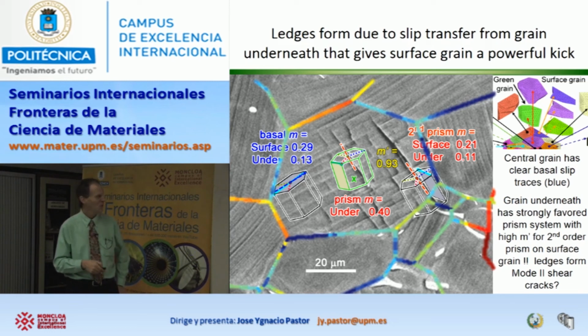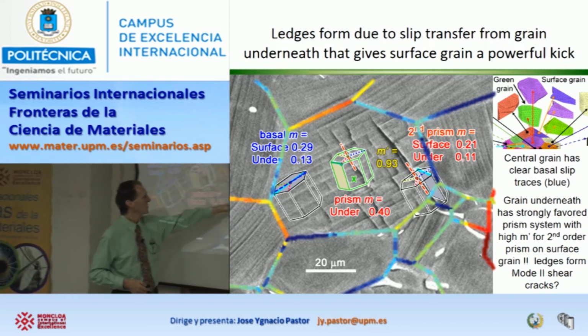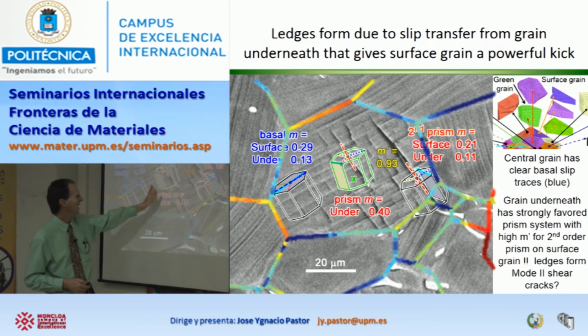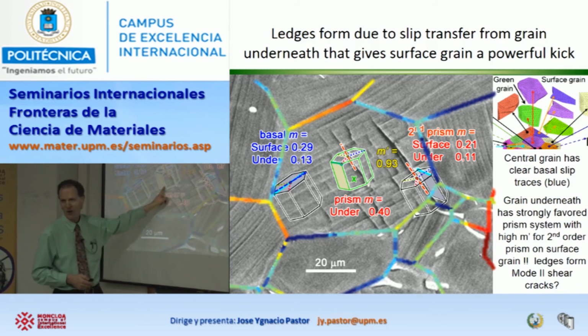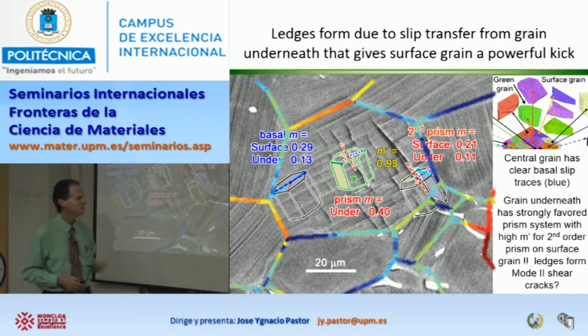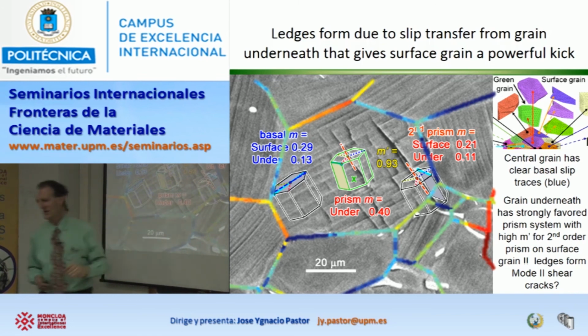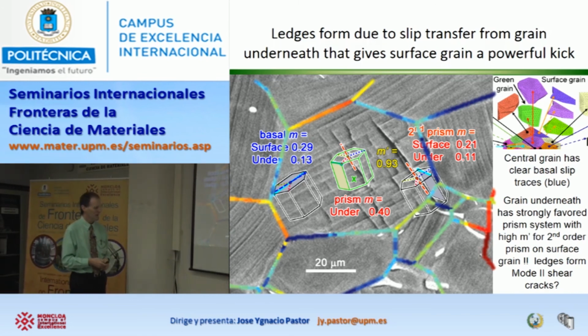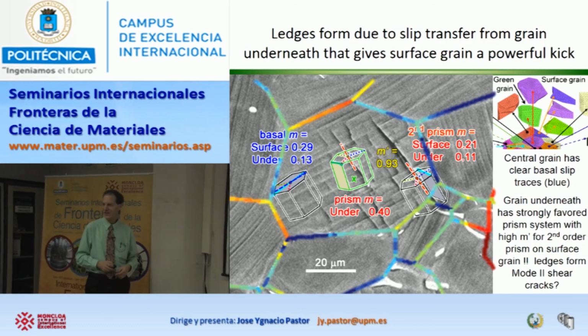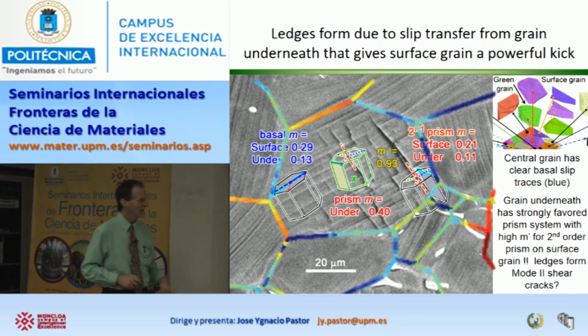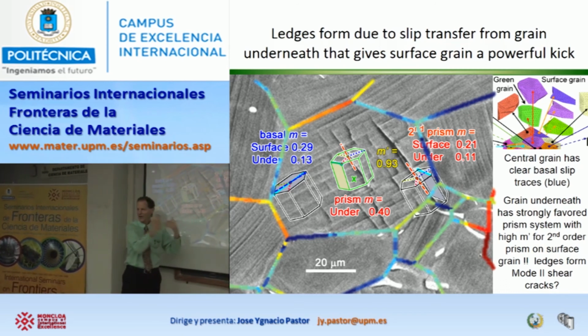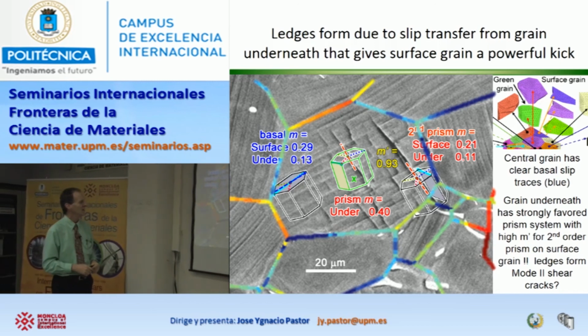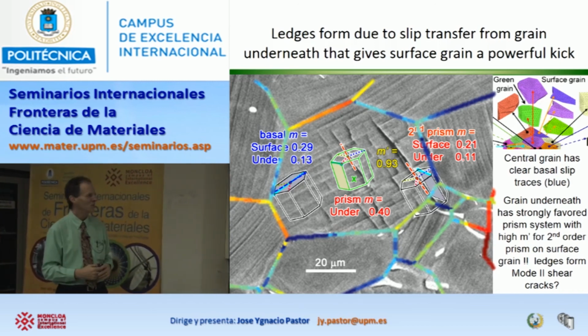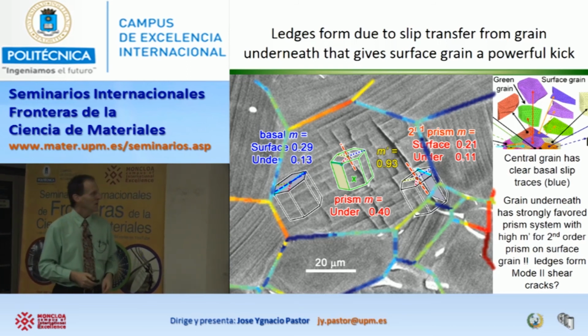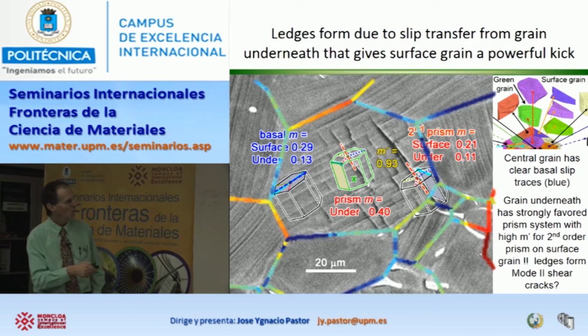But more interestingly, we were also able to work out maybe a reason for why these ledges happen. There's a grain underneath that has a high M prime parameter for slip to go from the grain underneath to line up with this slip system here. But this is a strange slip system in hexagonal metals. It's a second order prism slip, and that's never been seen that I know of. So it's possible that these are not slip, it's actually a shear crack, where we're getting cracking along the a plane that normally would not slip. So maybe that accounts for what these funny features are.